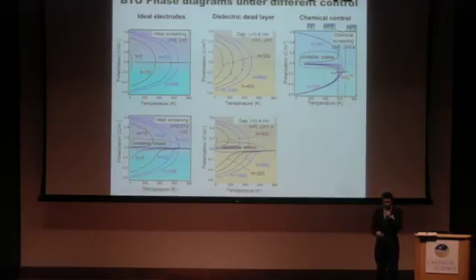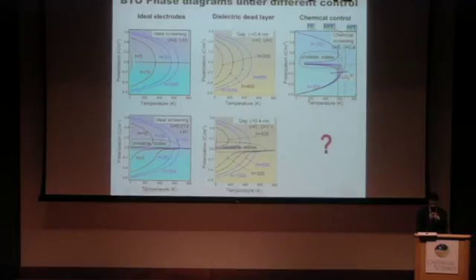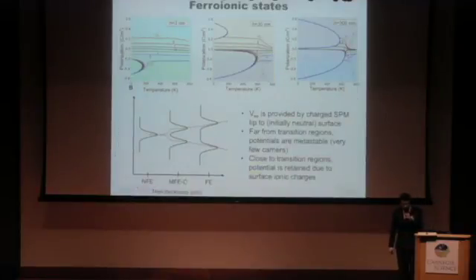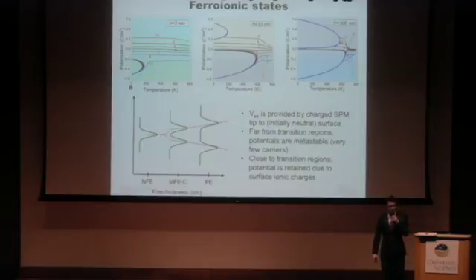But what happens now when we want to try to apply potential for this particular state here? That's the more interesting case, and so I'm going to explain to you what happens here. It's quite interesting. If we start with a 3 nanometer film, you will see that in fact at 3 nanometers, there's only one polarization state that's stable, and it's only at very low temperatures. But by applying potentials, you're able to stabilize all different types of polarization states here.